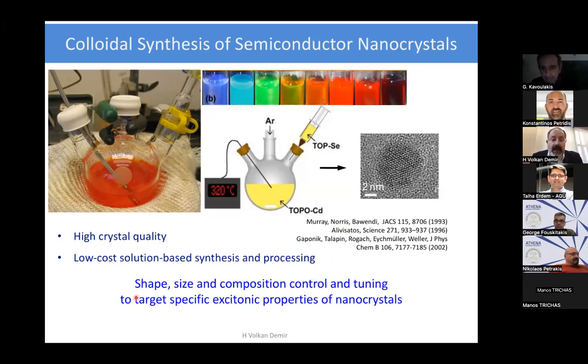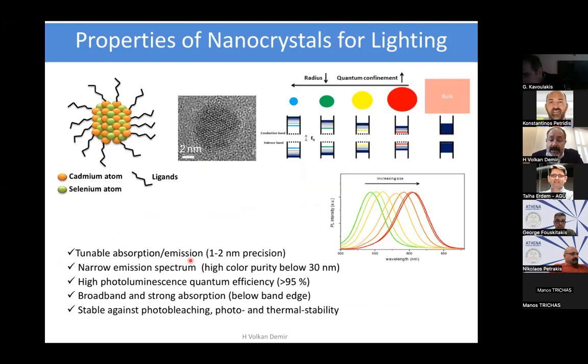And today, we can control shape, size, and composition. We can fine tune to target specific excitonic properties. And indeed, this is quite reproducible, particularly for the routes that are well nailed down, where we can hit the same peak emission wavelength or peak excitonic absorption within 1 to 2 nanometer precision. And to me, this is a really exciting and indeed great success of the whole community.